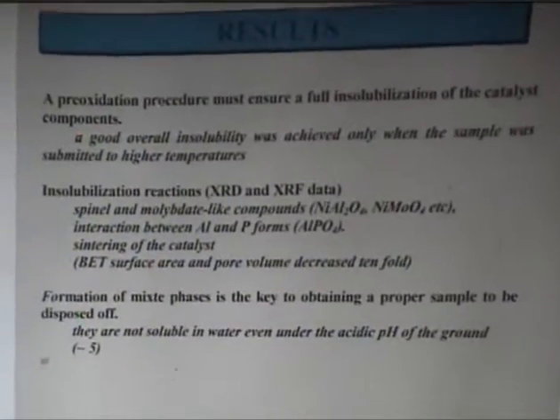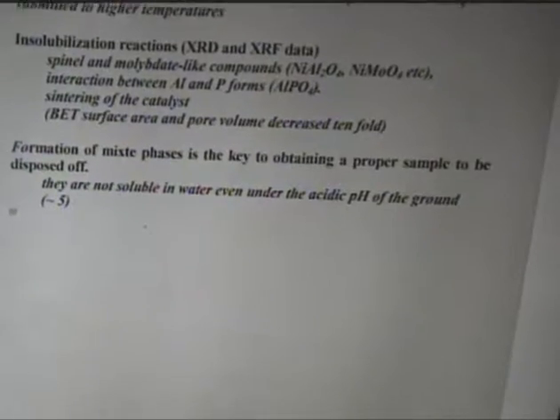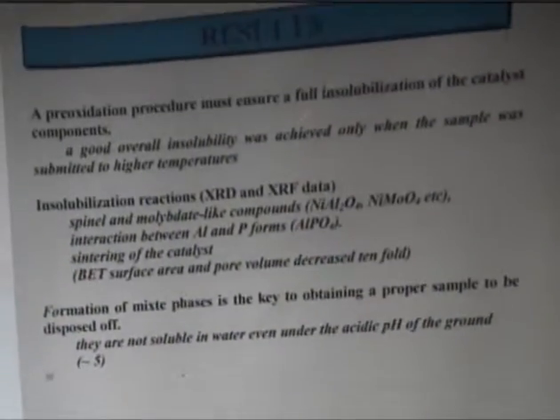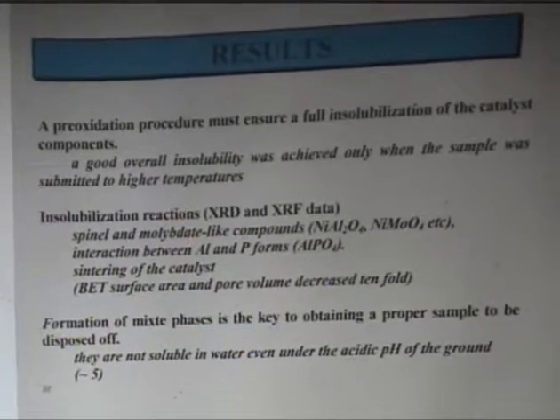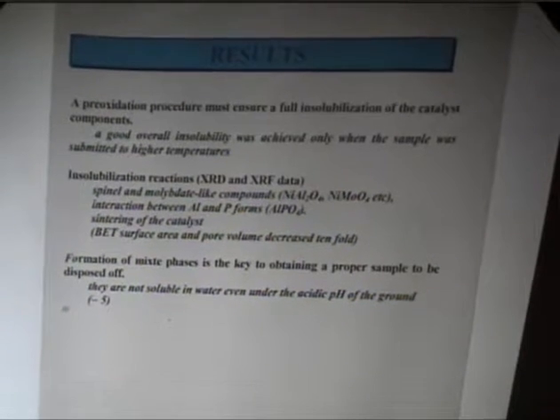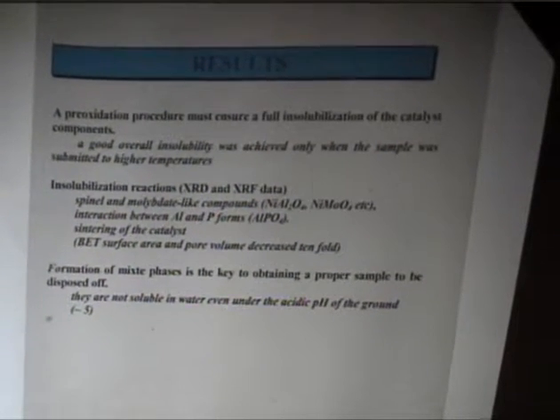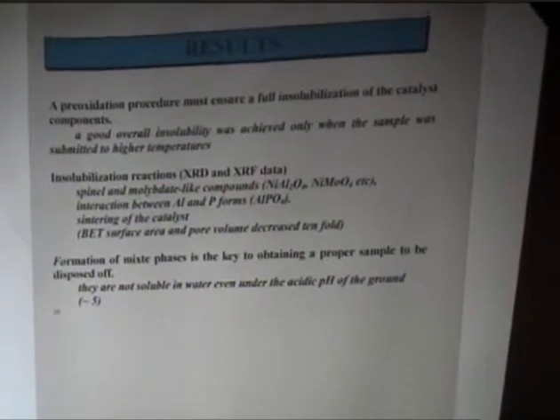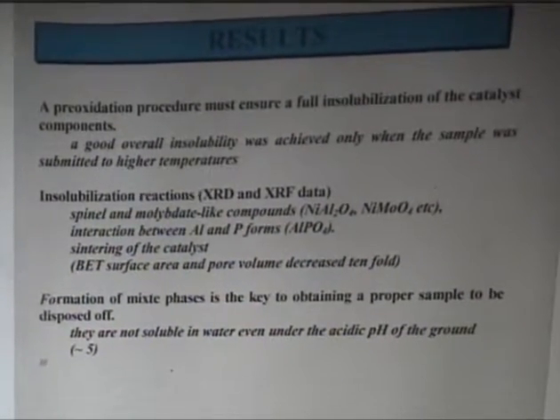Preoxidation procedure must ensure a full insolubilization of the catalyst components. And this overall insolubility was only achieved when the sample was oxidized at very high temperature levels. For this catalyst oxidized at 1273 Kelvin, X-ray diffraction and fluorescence data showed the classical results for hydrotreating catalysts submitted to high temperature levels: the formation of spinels and molybdenum-containing compounds, also interaction between aluminum and phosphorus forming aluminum phosphate, and also the sintering of the catalyst.